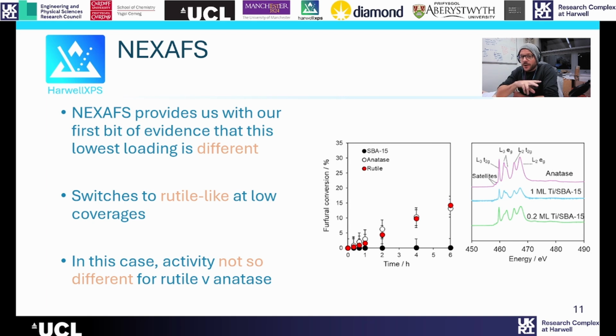So fortunately at Harwell, we have access to NEXAFS on the B07 beamline VerSoX. You can access this through the HarwellXPS website via rapid access. NEXAFS finally gives us an indication that we do have some different chemistry going on. Our low loading catalyst actually reported a rutile-like structure, unlike our other materials. So great, we've finally seen some kind of difference. But hang on, if we look at our reaction profiles, rutile and anatase don't really seem to perform very differently. So perhaps this isn't the only thing that's affecting our initial rates.